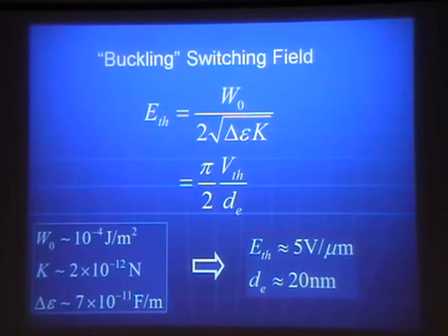And now we are trying to reduce that number by manipulating the way the pattern is being created, using different alignment materials, using different irradiation protocols, and all of those tuning processes are contributing to reduce the switching voltage. And we have so far achieved about a factor of 10 reduction. So we're fairly close.